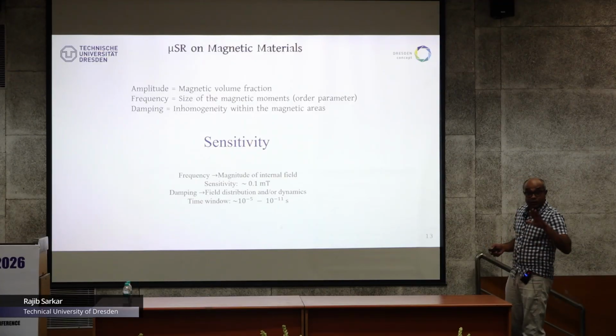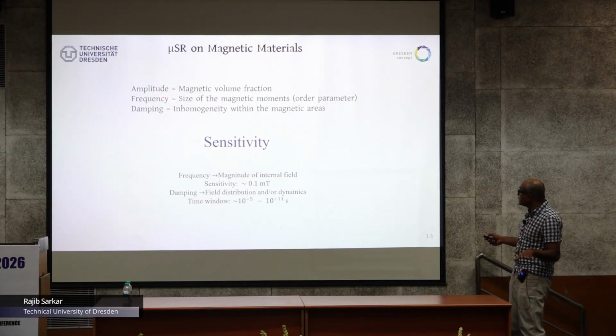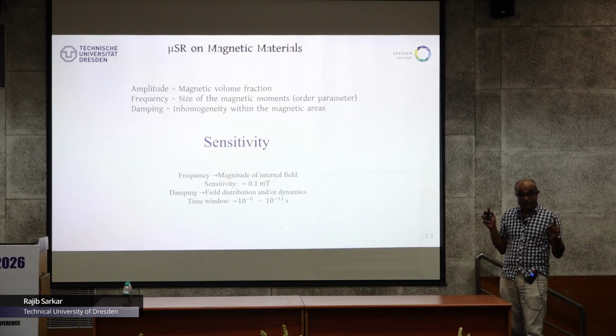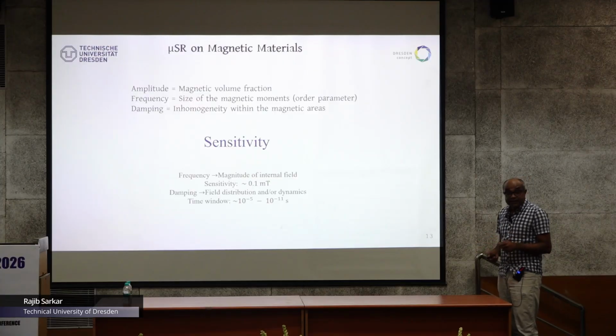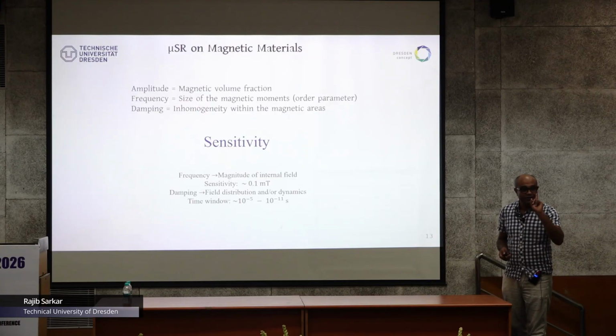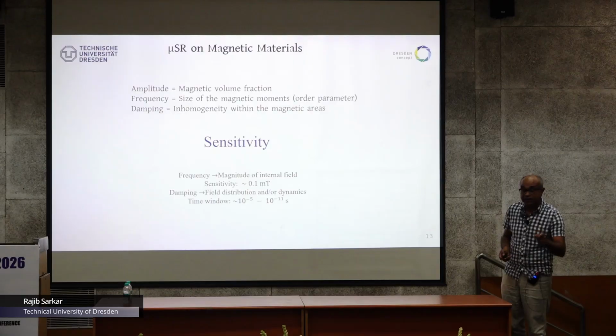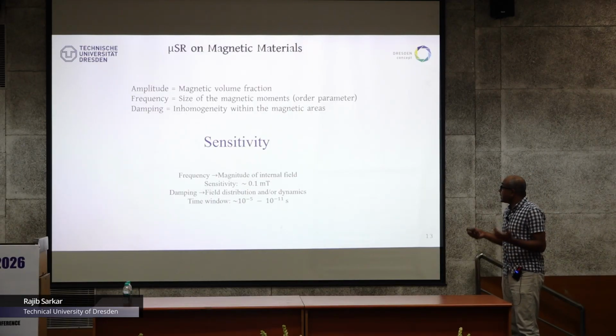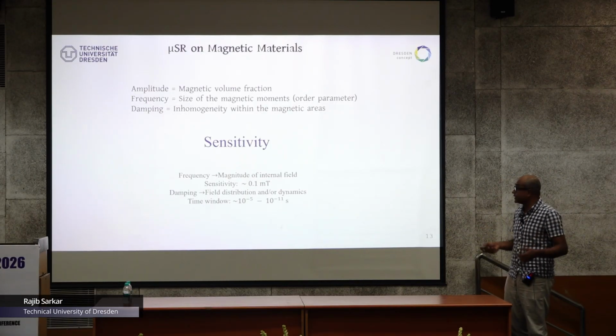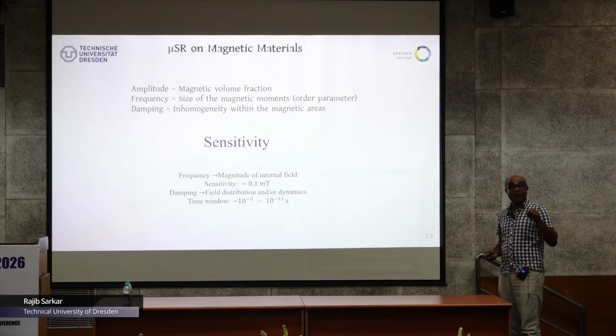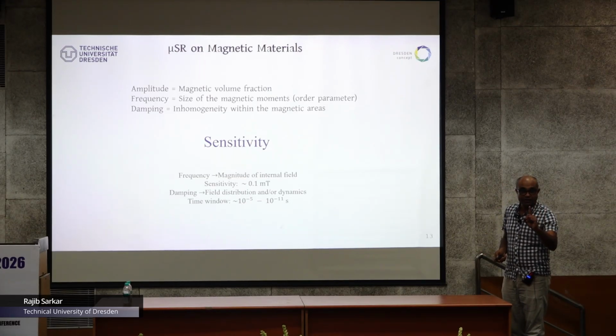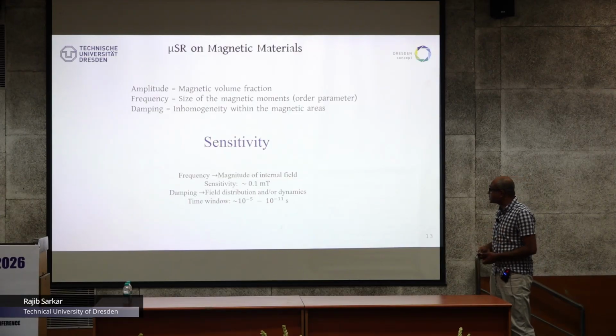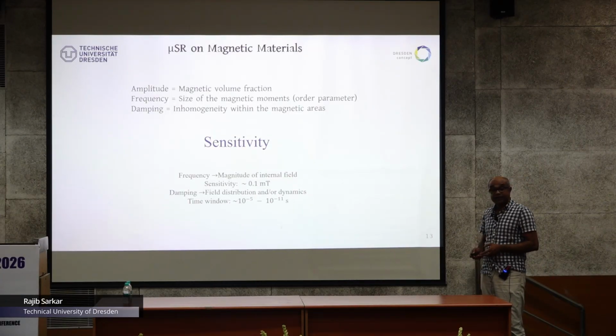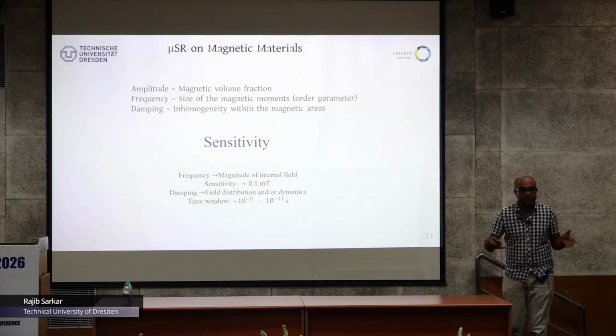Okay, so what information can it give you? As Moik informed a little bit, the magnetic volume fraction, yeah. So how much homogeneity in your sample this can provide. It can give you the frequency, that means the order parameter, not direct but an indirect effect of the order parameter. And of course this damping, this is the inhomogeneity of the spins, this can give. And it has a sensitivity of 0.1 millitesla, that means 1 Gauss it can track. This is quite sensitive. And of course the fluctuation time window is 10 to the power minus 5 to 10 to the power minus 11 seconds, but it depends on which muon source type you are using.